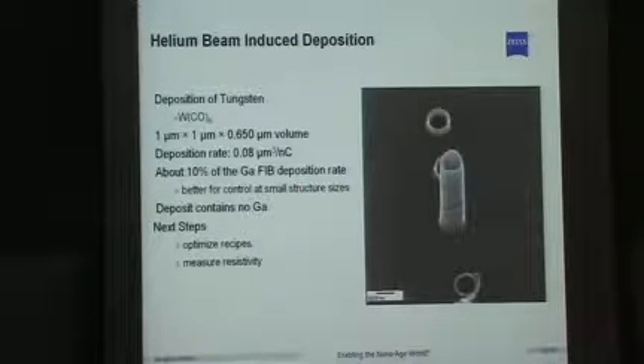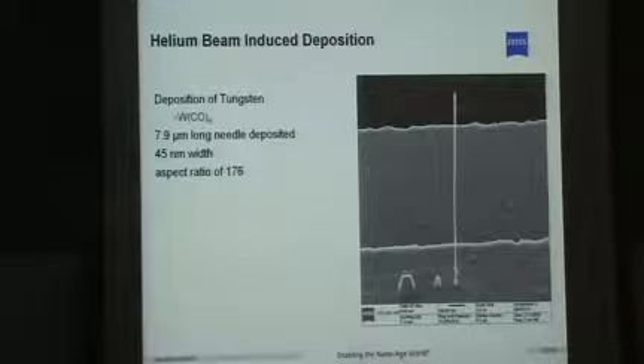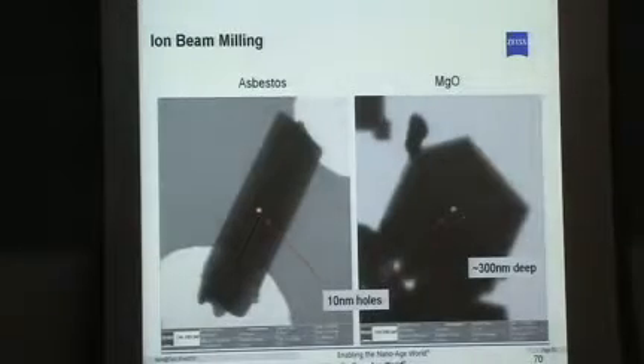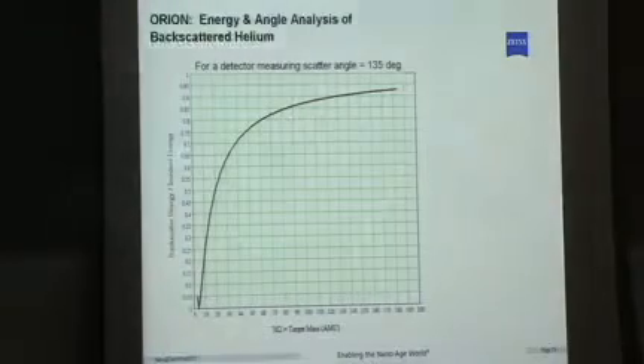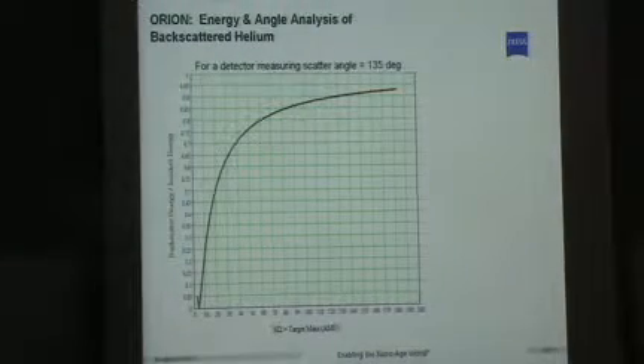Here's something that we built up, these little nice cylinders. Here's something even taller, about 45 nanometers wide and 7.9 microns tall. That was made out of tungsten. And here's a hole that we bored. This is a hole around 300 nanometers deep and around 10 nanometers wide. I'm sure there's people out there who want to have holes of such high aspect ratio. I'm going to go over the rest very briefly because I want to leave enough time for questions at the end.